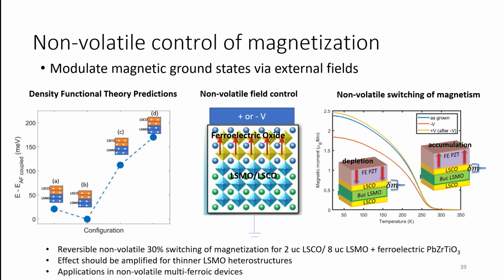But we had a colleague do some DFT calculations for us, and he found out that the magnetic structure that we found experimentally was indeed the lowest energy state of the system, where the LSMO and the chromium spins are in opposite directions. But more importantly, he finds that very close in energy, even though it's a high energy state, it's a state here where all the spins align themselves in the same direction.